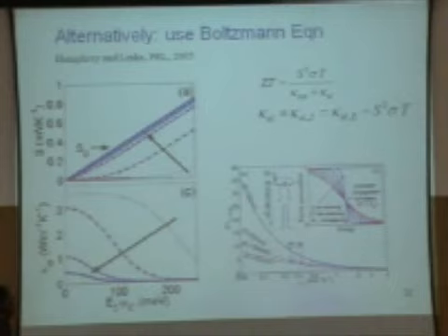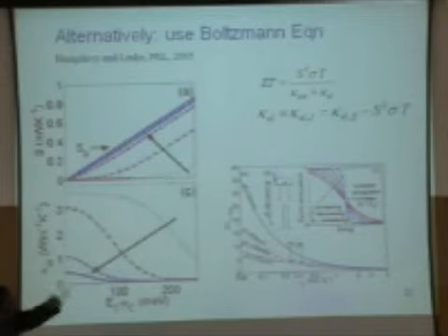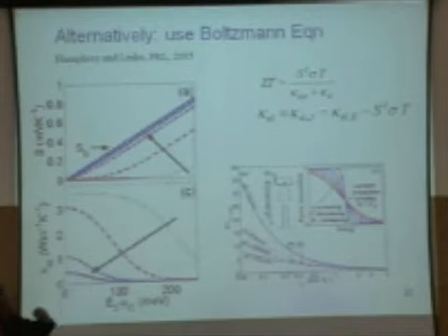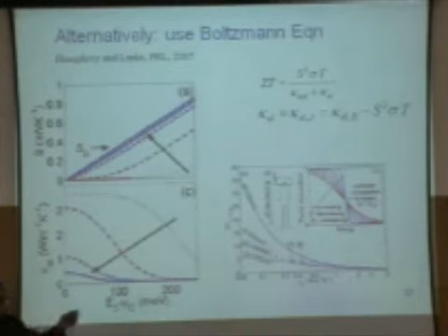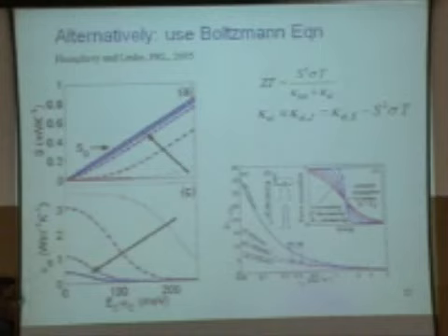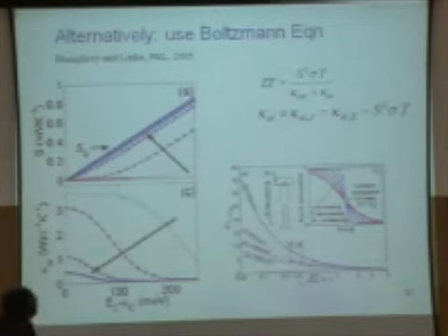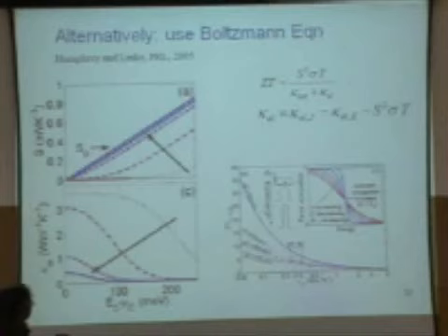I had a slightly different idea: don't change the chemical potential, which is again connecting, but maybe allow for different energy levels at the hot and cold end, but that would, of course, again be one shot. You change the energy levels so that E minus mu is a constant. So you synthesize charge. Maybe nature has done that, makes various molecules as sites where the electron goes here, here, here, optimally, so that that factor remains constant. There's no entropy change involved. This is an idea which I still like, and I think Linke is working on it. I talked with him once in a while. Humphrey, who is a graduate student, proposed this. She has moved on, working on quantum transport, but let us see.